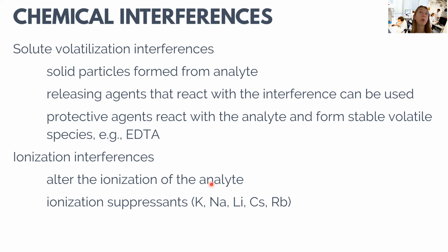To overcome this effect, there is a possibility of adding releasing agents. So these are other metal salts that can be added to the sample, but these then preferentially react with these anions and therefore release our analyte from the interference. Or another possibility is to use protective agents. So these are usually a reagent that form a very stable complex with our analyte. This very stable complex is then more stable than the analyte interferent complex, but the newly formed complex is also volatile and helps therefore our analyte to become gas phase atoms. And a very commonly used protective agent is EDTA for very many methods.